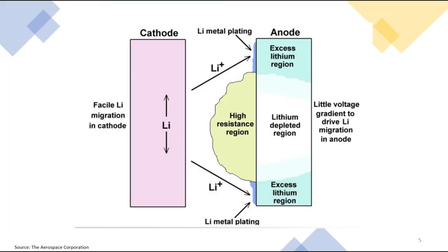Exactly as you were describing, if you imagine you have your anode here, in cross-section view, when you're charging, you're trying to push lithium into that anode to store that. And that is mass diffusion, and the lithium is arriving from one side, but then it has to diffuse through your anode. And that's all rate balances. But if your lithium is arriving at a higher flux than it can diffuse into your anode, it's going to start backlogging and accumulating on the surface. And eventually the driving force is going to be strong enough to cause plating at that interface. Usually once that's happened, you're out of luck. It's generally impossible to recover that lithium, at least fully. And so you've lost capacity.